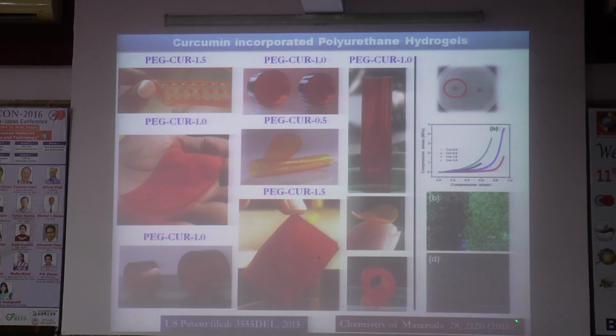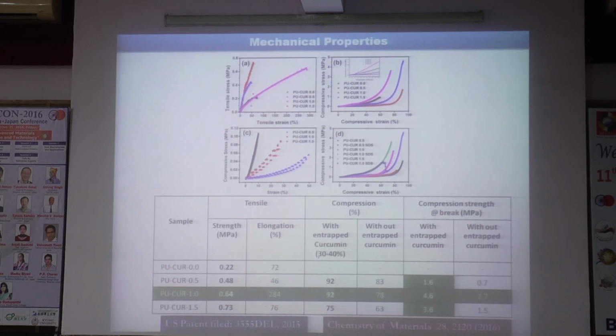Recently we have published a paper in Chemistry of Materials. Of course, they have excellent mechanical properties. Look at this, with the curcumin, it has almost got 4.6 megapascals mechanical strength. Because of the curcumin inside, the dissipation of energy takes place through curcumin, and the strength of the hydrogel has increased tremendously.